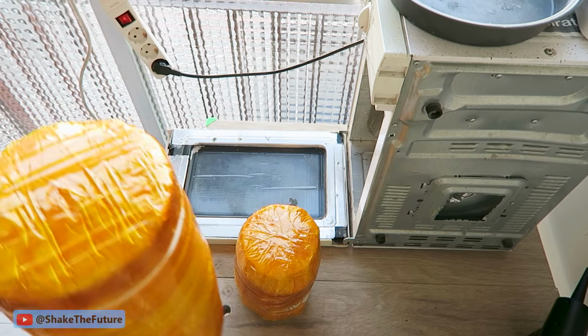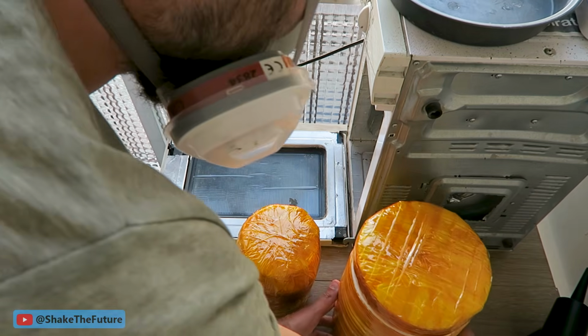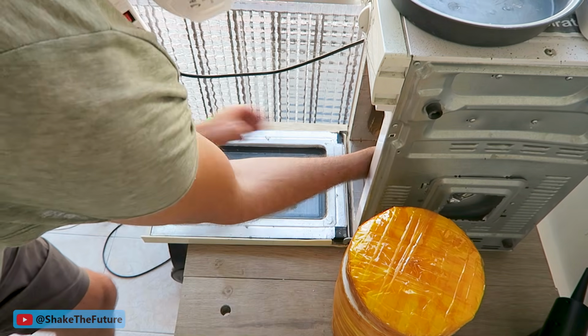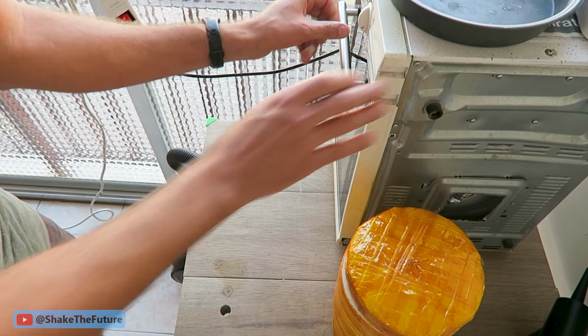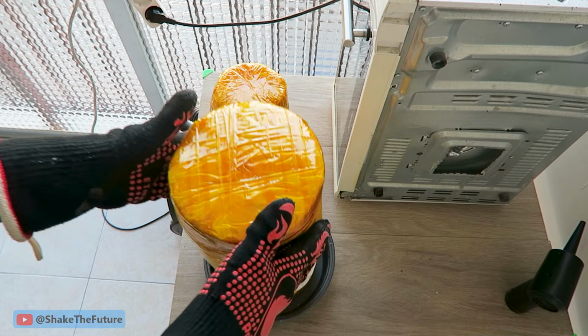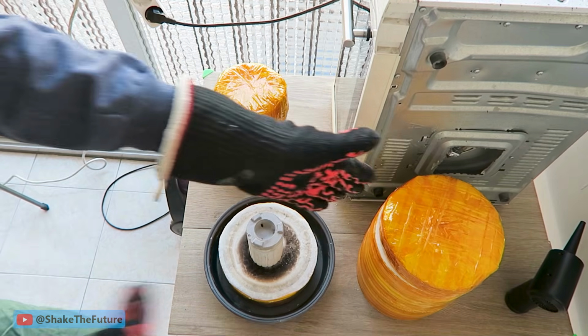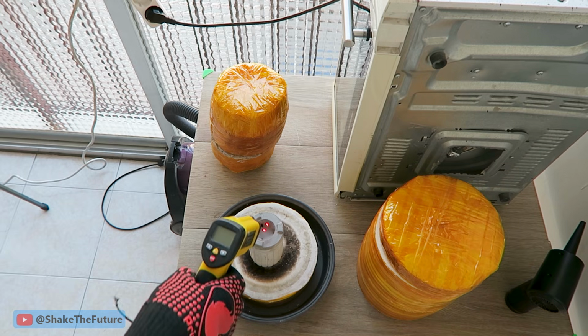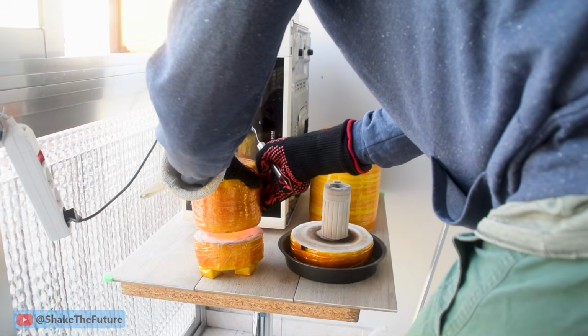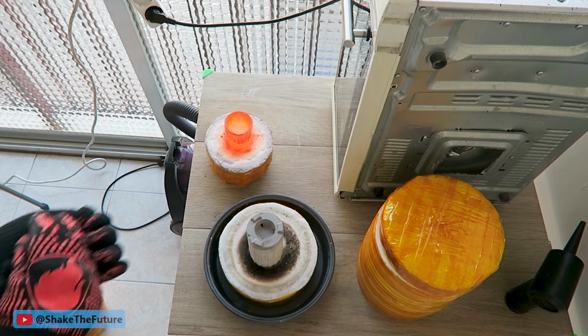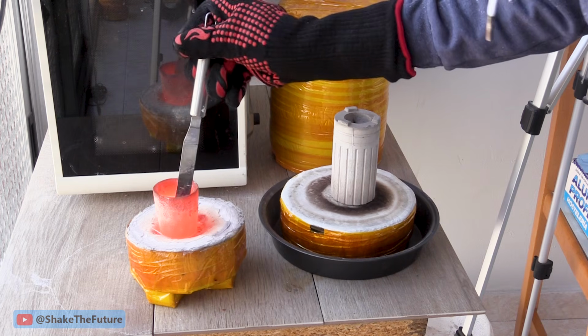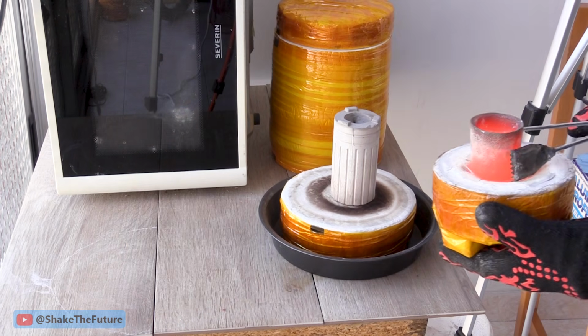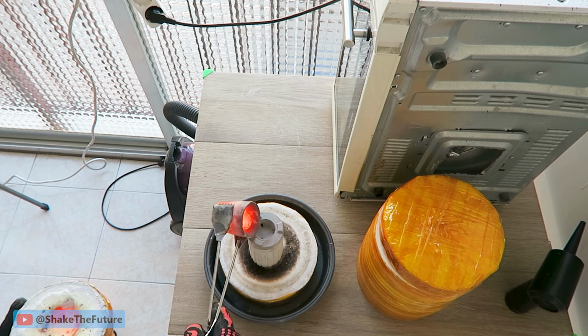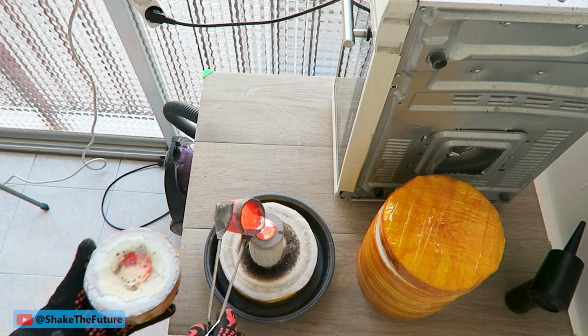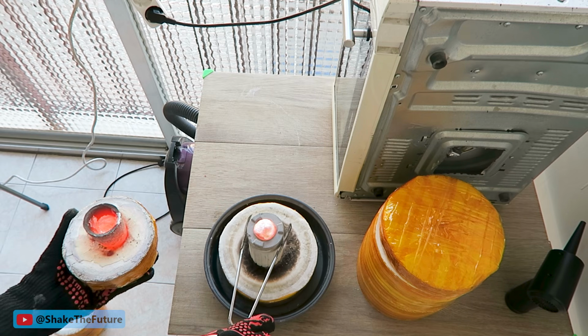I'm gonna melt some aluminum and we'll try to cast the funnel. While I was melting the metal, the mold cooled down to approximately 350 degrees Celsius. By the way, whenever I do Lost PLA casting, my molds never reach 500 degrees Celsius. By the time I cast metal, they're usually between 300 and 400 degrees.